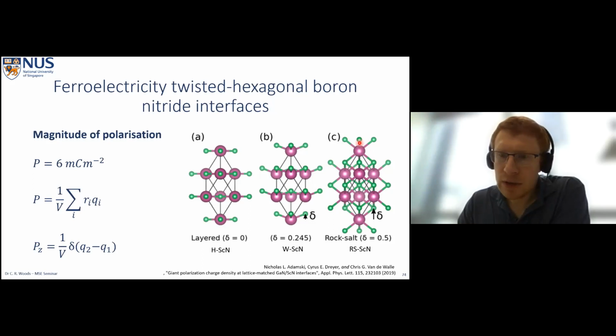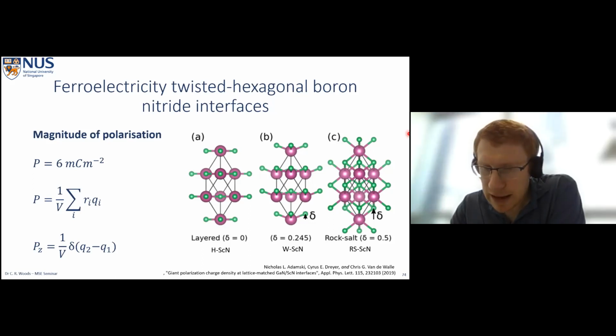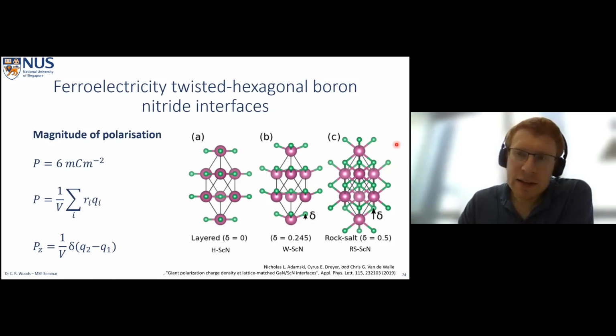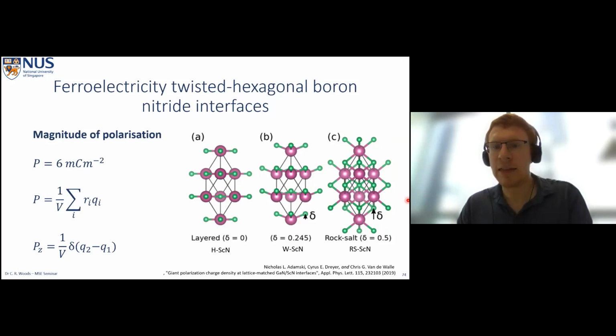And we can do this by analogy or by looking at the other Group III-nitride crystals. And these are quite famous for having large spontaneous polarizations, particularly in their wurtzite form. So this is scandium nitride, which is expected in its hexagonal form. So you're looking through the planes here. So this would be the hexagonal form. You're looking at each layer. This would have 0 polarization. And when we start to displace the nitrogen atoms up between the layers, we start to introduce a polarization.